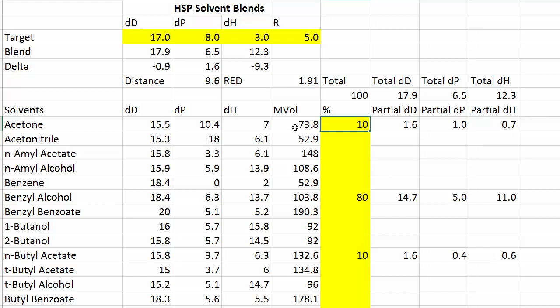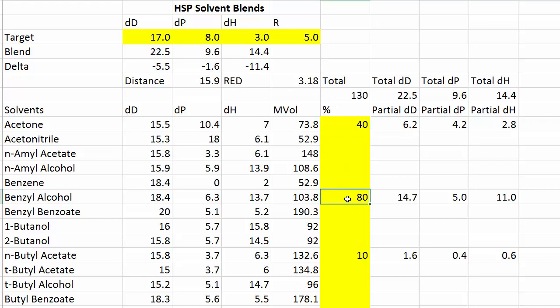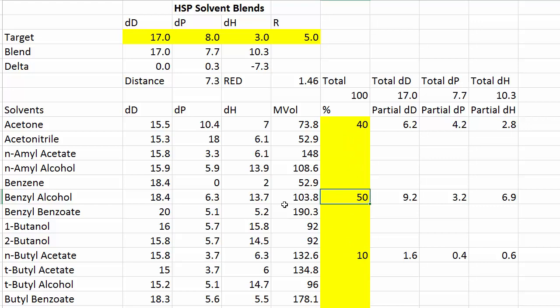How can I optimize it? Let's increase a bit of this to 40% — then we have weird numbers because I've got 130% here. So let's reduce this to 50%, and now I've got 17.0, 7.7, 10.3. It's a very poor fit there, but it's at least closer. With more intelligence I could work out a solvent blend, or using the optimizer I could optimize this blend to get the perfect fit. There you are — two rather powerful tools which will help you formulate your adhesives using HSP.